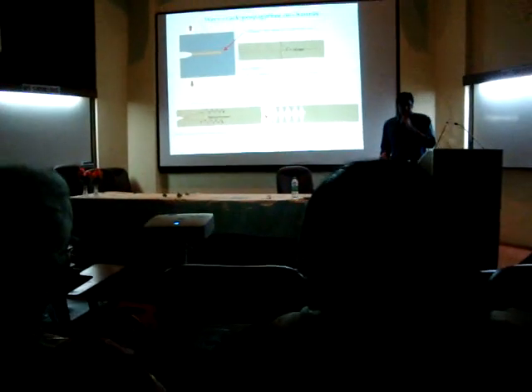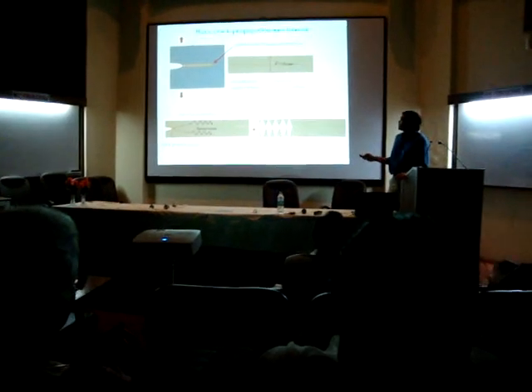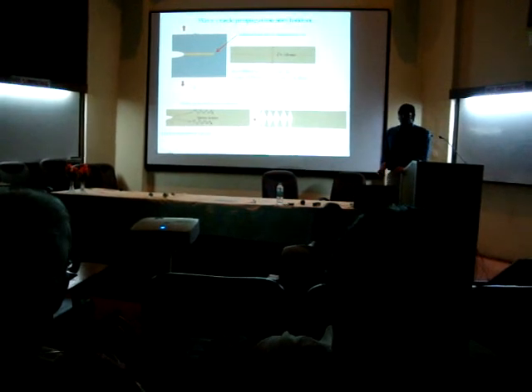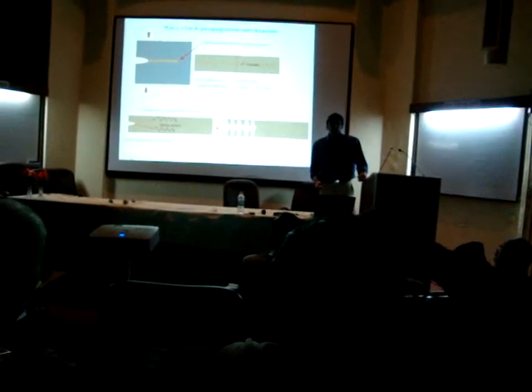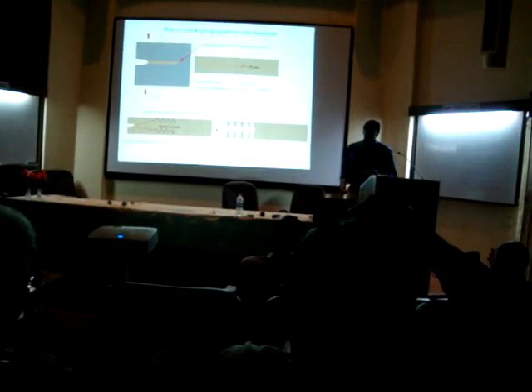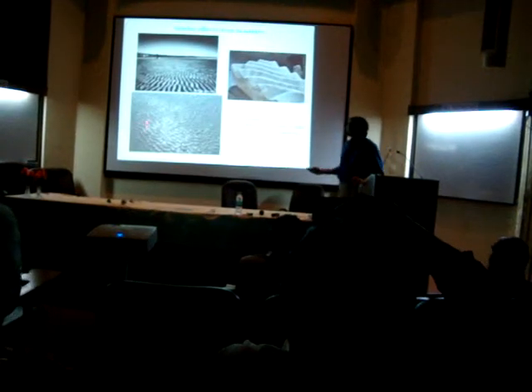So one particular way of justifying it is that ahead of the notch tip, when you apply stress, the heat increases and your crack starts propagating. Since your crack is propagating with a high velocity, it's a dynamic crack, and it will release a lot of matter waves which can interact with the fluid medium which is formed in this layer, and that fluid medium can influence wave-like patterns. This is one of the mechanisms which we want to suggest and also investigate in future, because such studies of matter waves on liquid mediums, on fluid mediums, have not yet been done.